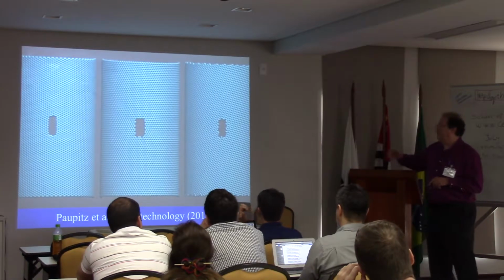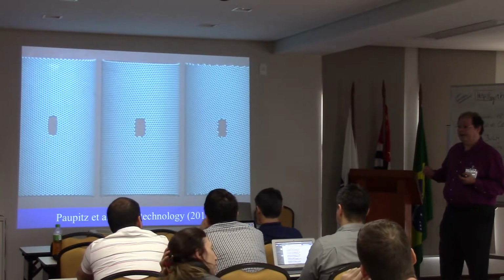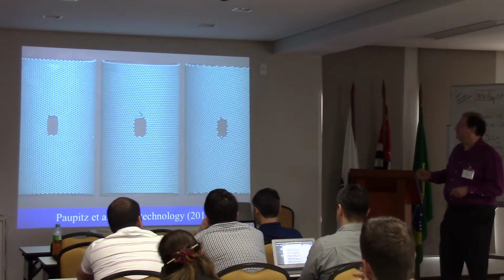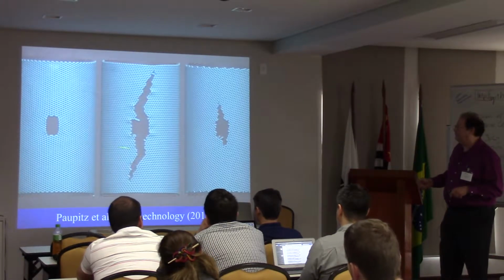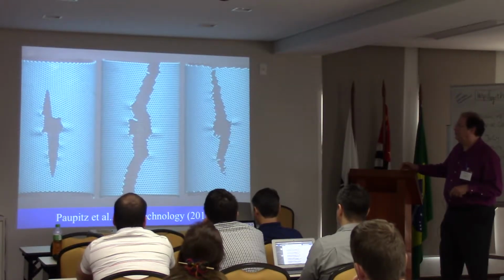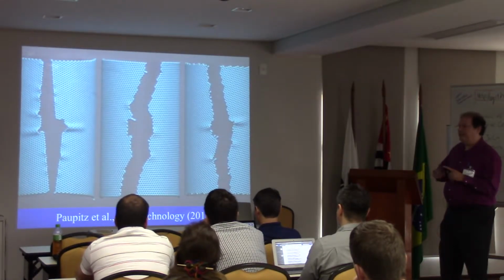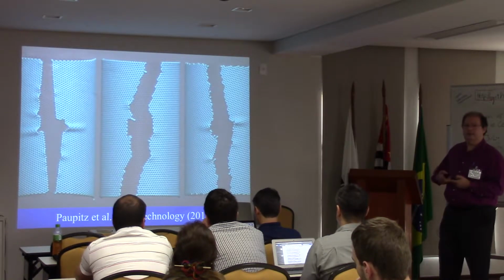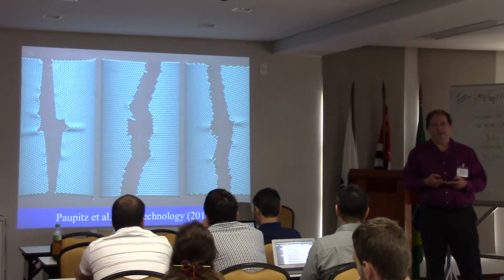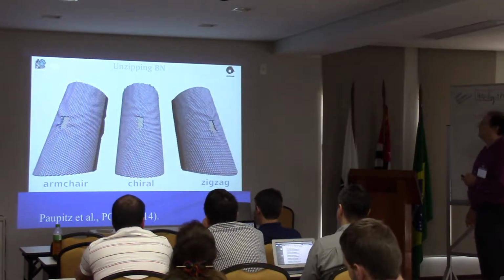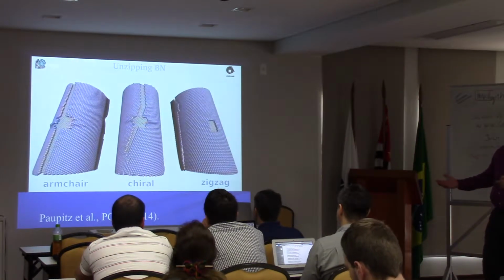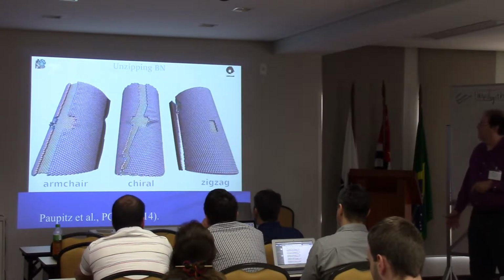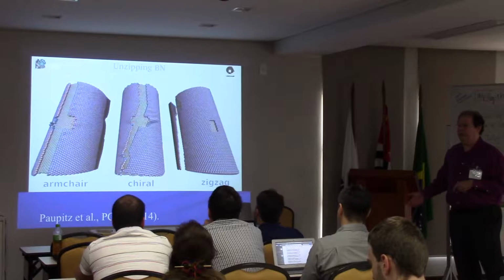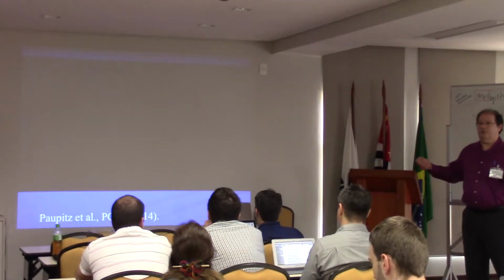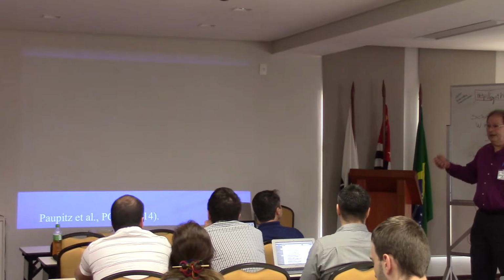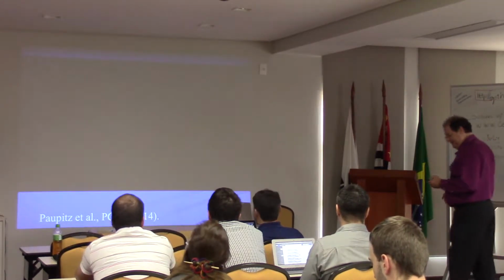The question is, if I try to break carbon nanotubes, is chirality important or not? So we ran the simulation for the armchair, zigzag, and chiral, and you see, for carbon nanotubes, the chirality is still important. The time of breaking, the way of breaking, the pattern of breaking, it's still chirality dependent. If you do this with boron nitride, it's a brittle material. So for boron nitride, the chirality is not important because it breaks much earlier. So there is no time for the tension to dissipate. It accumulates, it breaks. So in this case, that is not important.